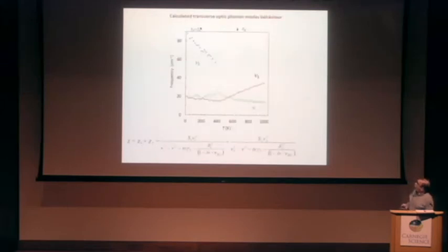And these are the results concerning the phonon modes. We observe two phonon modes. One of these modes, nu 1, softens on cooling and then is almost frequency independent, and the second one appears below about 350 K.